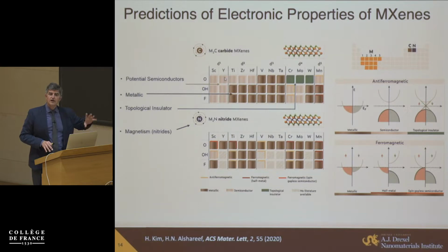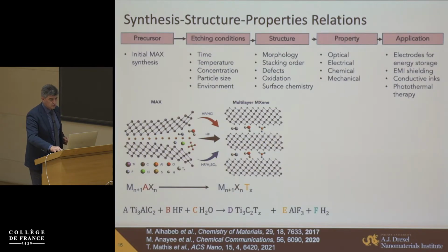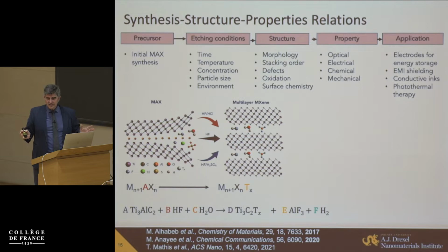Dmitry Talapin from U Chicago showed superconductivity in niobium carbide terminated by sulfur, selenium, and tellurium in 2020. A number of other things have been shown here. But what is important is that all these things are controlled by the synthesis of this material and its composition. Material scientists usually draw this kind of triangle: synthesis, structure, properties, application. I don't think it's really a triangle. In my opinion, it's always a sequence.